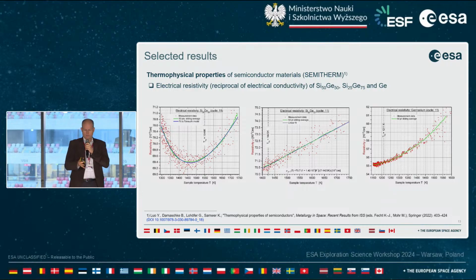And then if you go very deeply into the undercooled liquid regime, and it's particularly prominent for the silicon 25 germanium 75, if I see that correctly, then you see that it's increasing again, and resistivity is very sensitive to structural ordering in the liquid. This resistivity increase is an indicator that shows ordering in the undercooled liquid state. And it can be assumed that also in the other alloy, at least for germanium, you see the bend over, and if you were able to undercool the sample more deeply, you could envisage that this is also increasing. It's a nice contribution to a long-standing discussion about ordering in liquid transitions in these materials.